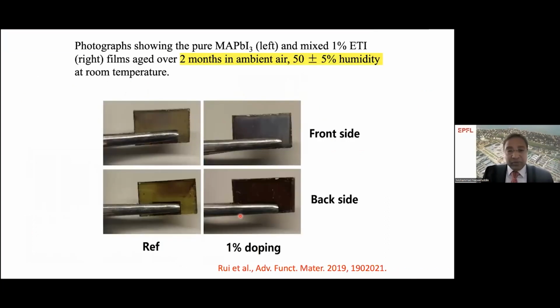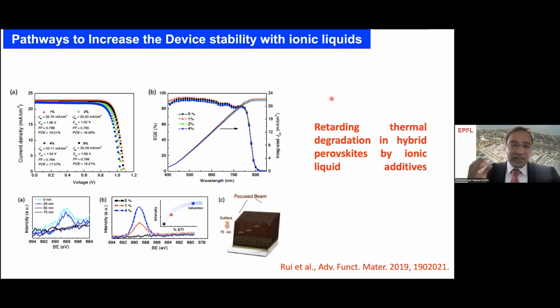They are quite the same. But if you look at the actual cell with 1% of this ionic liquid deposited, this is the front side and this is the back side. On the left side, you can see the reference. Without this ionic liquid, you can see that it's decolorizing. At the same time, on the back side also, it's decolorizing. So it shows that this particular ionic liquid, at ambient temperature and 50% humidity, shows extremely stable performance. Now, the question is, what is happening and how is it happening? So the data is shown here.